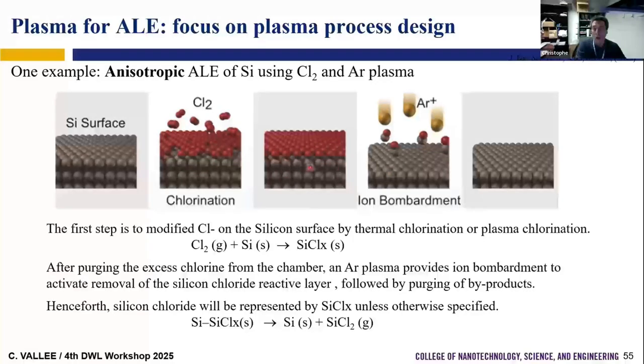So why do we only remove one monolayer? It's because the binding energy for the silicon atom in the bulk and the binding energy for the silicon bonded to chlorine is not the same. So usually we have a weaker binding energy for a silicon atom at the surface when we do chlorination than in the bulk. And you know that the sputtering threshold depends on the binding energy of the material. So if we have two different binding energies for this top silicon atom and the bulk, we have two different sputtering thresholds. And what we have to optimize is the ion energy, to be in between the two sputtering thresholds. So we only sputter the first monolayer and we don't sputter the second monolayer.